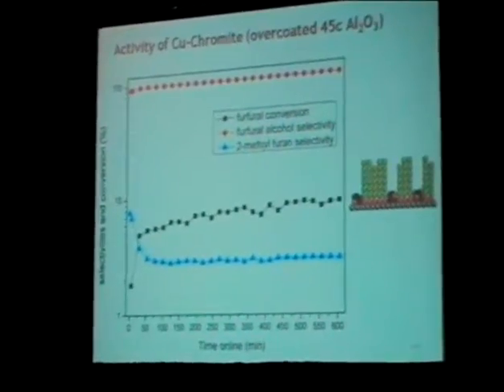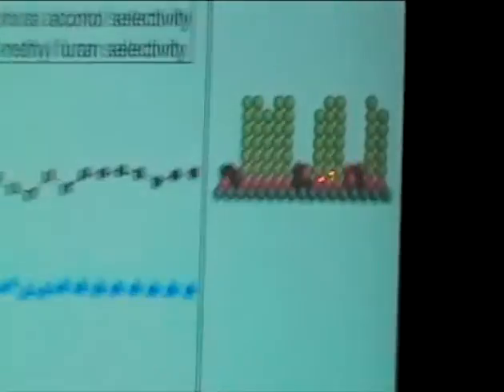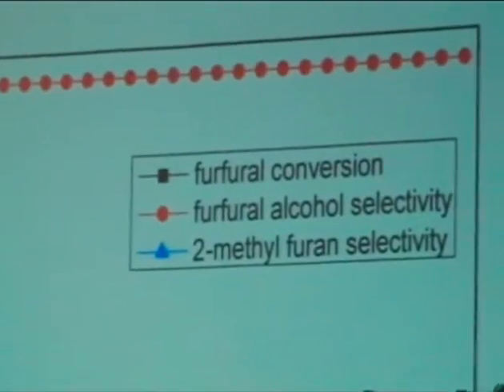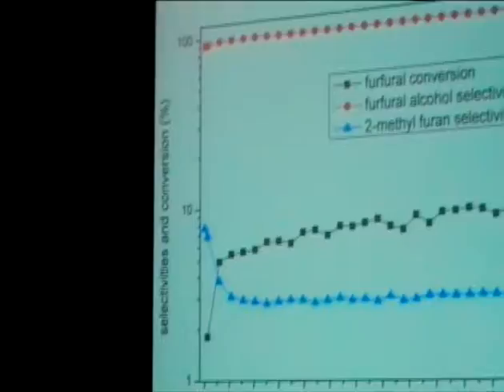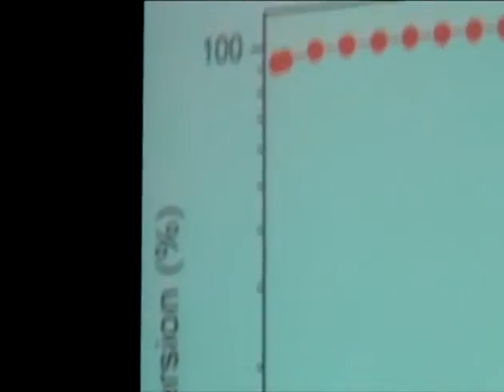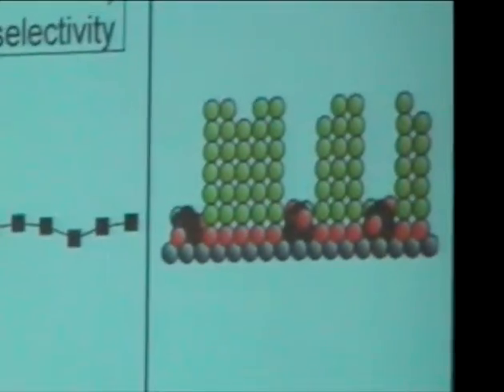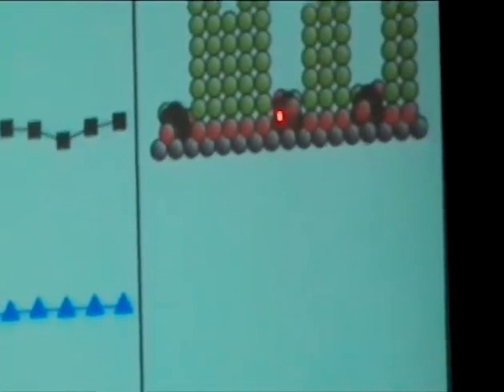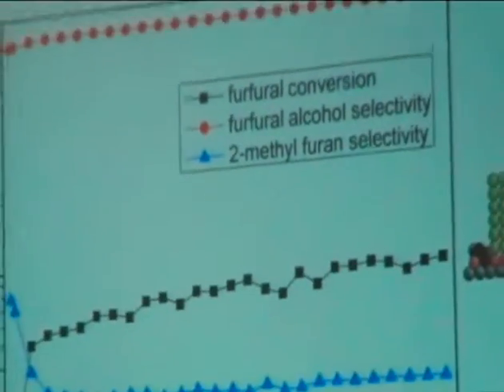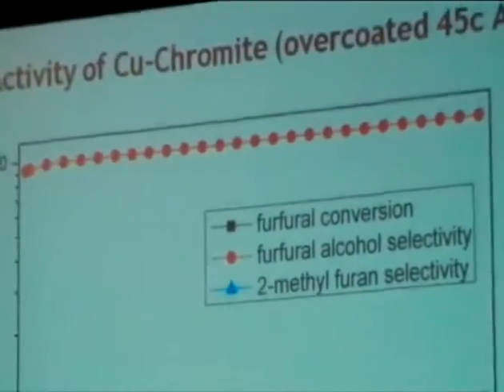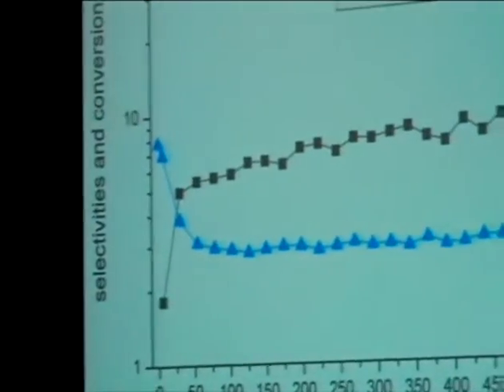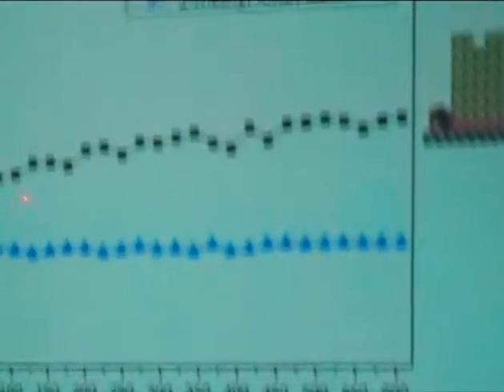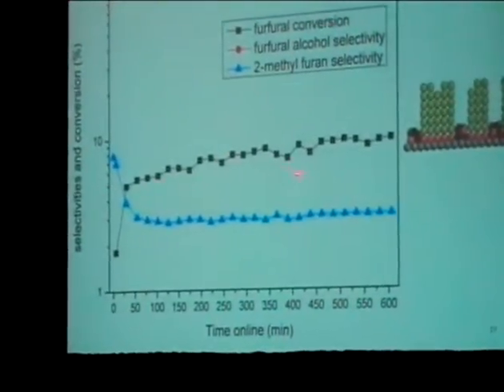So we started out with our copper chromite catalyst, and we've put 45 layers of alumina over that material, then calcined it at 700 degrees. So what we've got now is an alumina overcoating going over the top of our chromia here, and our copper materials still are open to the site here. You can see by the black curves here's the furfural conversion as a function of time on stream. And not only is it not deactivating, it's actually activating over the course of the time frame, and it keeps on going out there for several days.